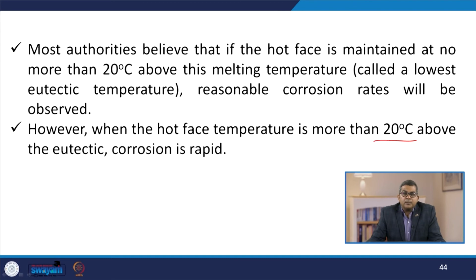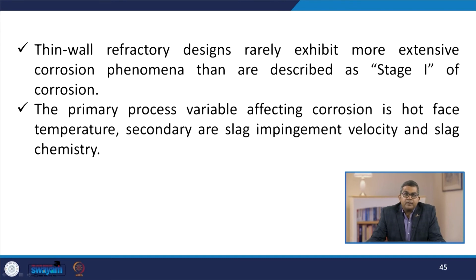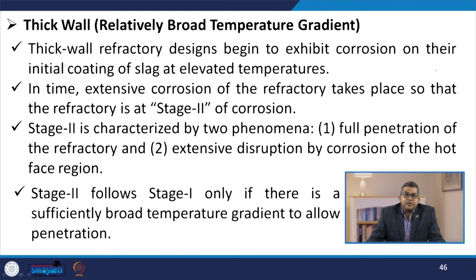However, when the hot face temperature is more than, say, 20 degrees Celsius above the eutectic temperature, then corrosion is rapid. Thin wall refractory designs rarely exhibit more extensive corrosion phenomena than those described as stage 1 of corrosion. The primary process variable affecting corrosion is hot face temperature; secondary are the slag impingement velocity and slag chemistry. Now, let us talk about the thick wall, that is, a relatively broad temperature gradient.